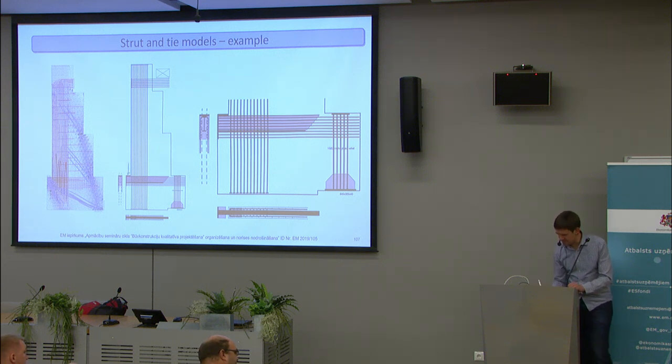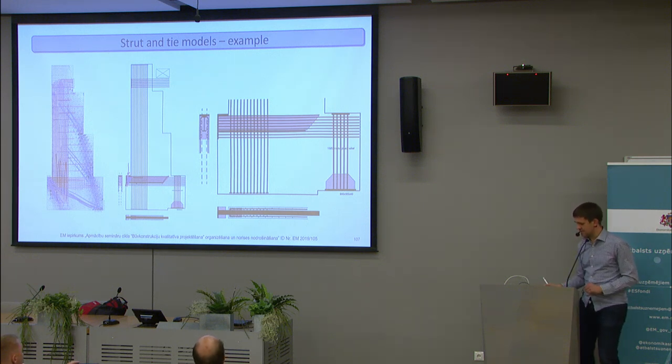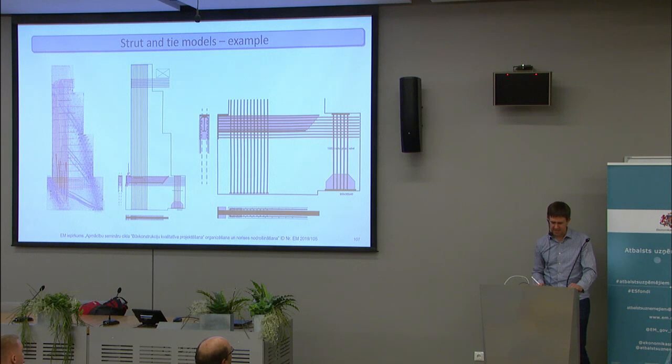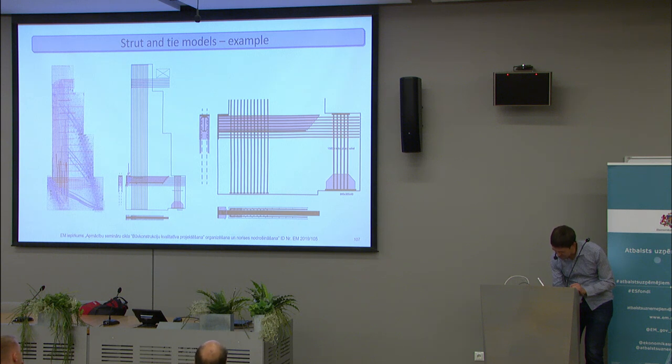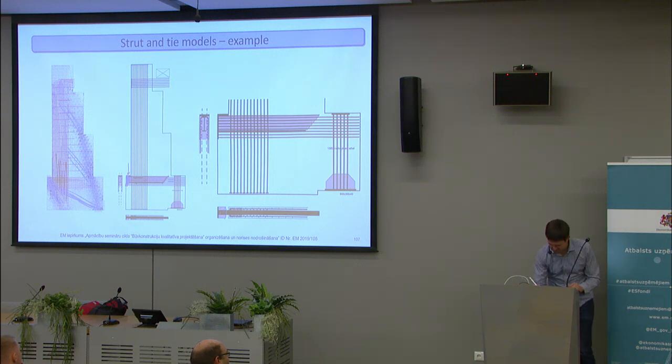So to confine the concrete in here, I put a steel profile in it and steel plates around it, so that concrete in this joint would be very well confined, because the concrete stresses reached almost 20 megapascals. So I used C40-50 concrete for that, but with the effectiveness factor, it would still be over the fcd limit. So that's why I put the steel plates in here to make sure that the stress is distributed evenly. And I anchored these rebars to this end plate to make sure that it's anchored well in the joint. So these are welded in here.